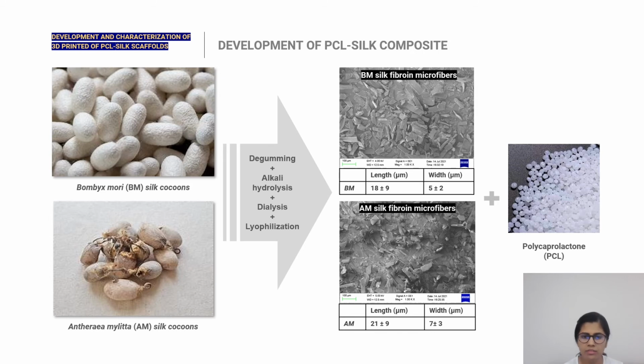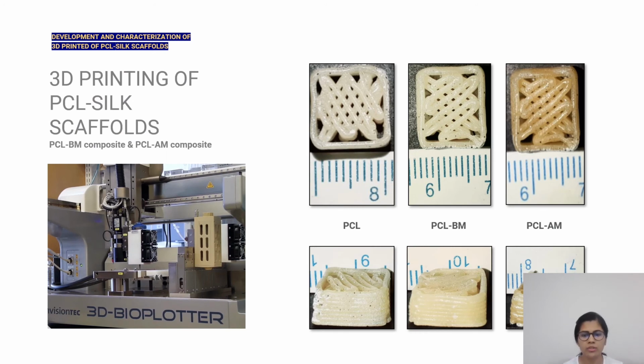These respective microfibers were mixed with polycaprolactone to form the composite via a process of wet mixing. And then we optimized all the 3D printing protocols: the temperature, pressure, speed, needle offset, and the laydown pattern. All these parameters were optimized to successfully 3D print the PCL-silk scaffolds.